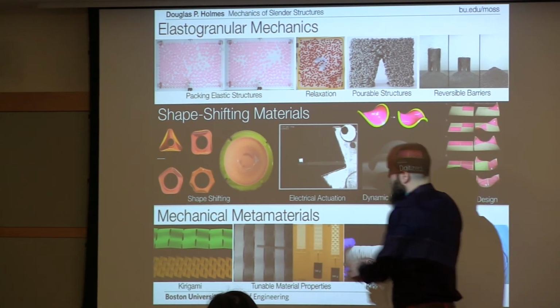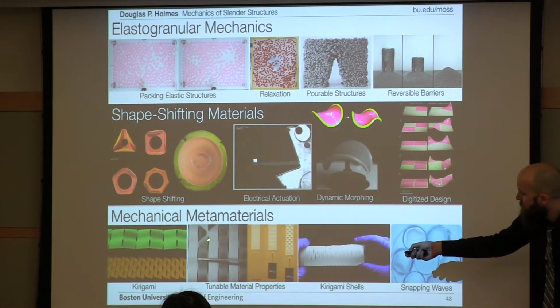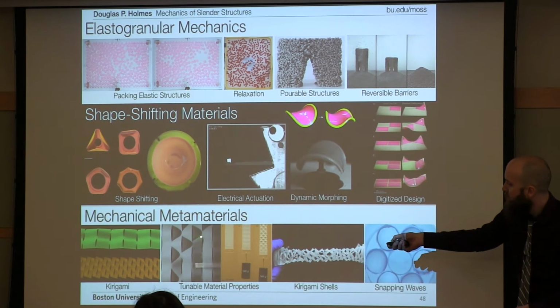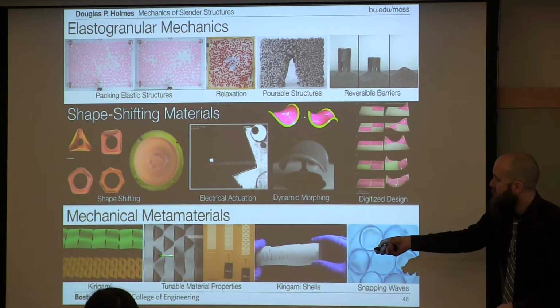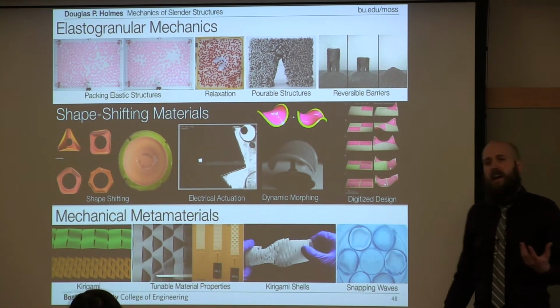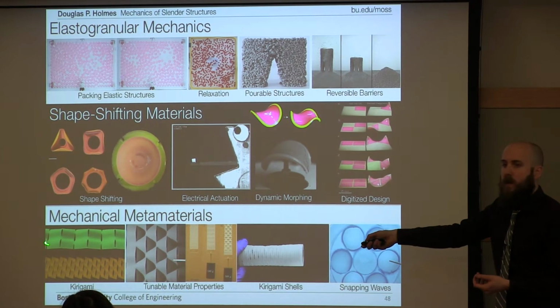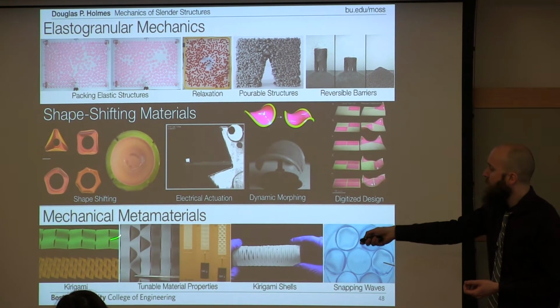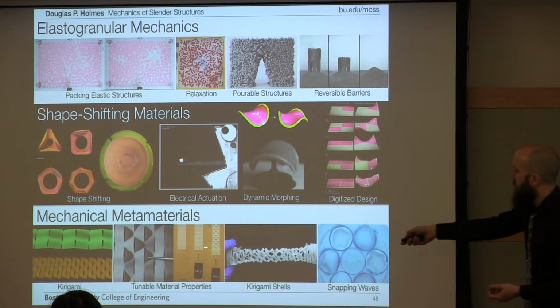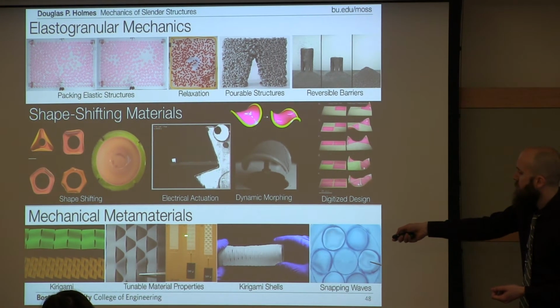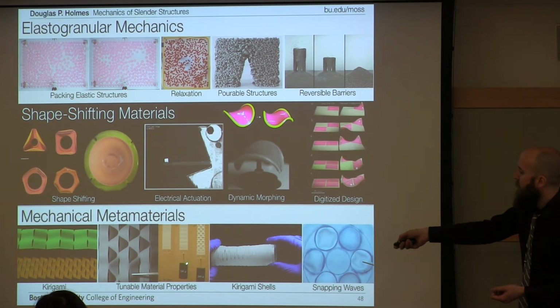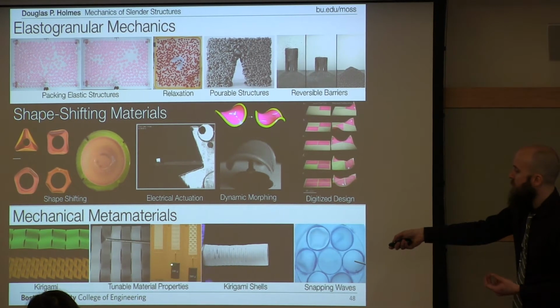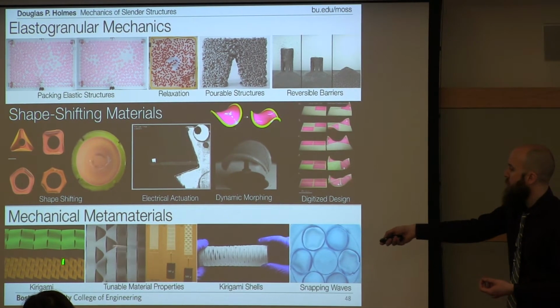This is a second shape, and if you poke on them, you can actually switch this shape to something that looks like this shape. So why does that matter? Because this shape, as you saw when it was getting passed around, is significantly stiffer than this shape, and you can see it here. When this shape corresponds to this shape here, it can hold this 500-gram mass much higher than when you switch it to this shape here.